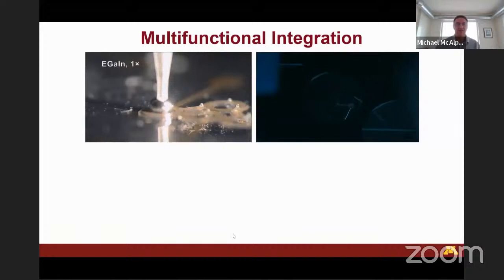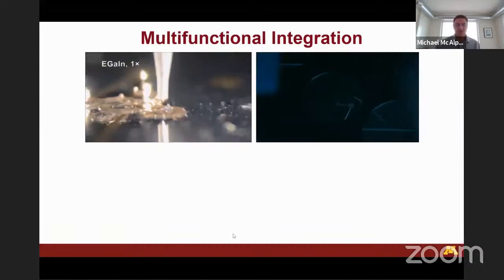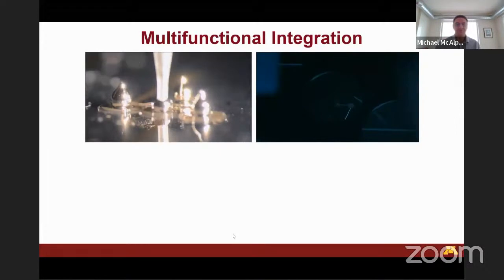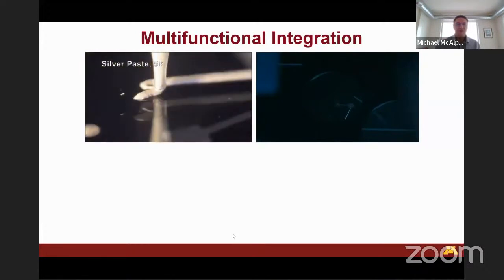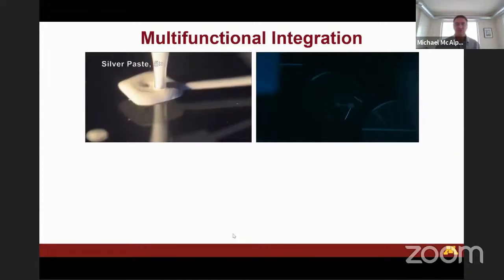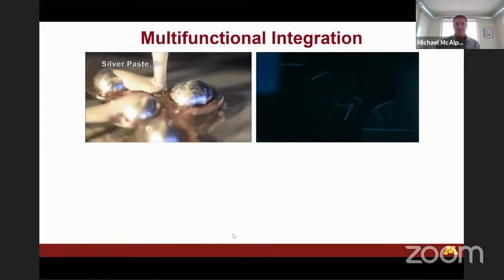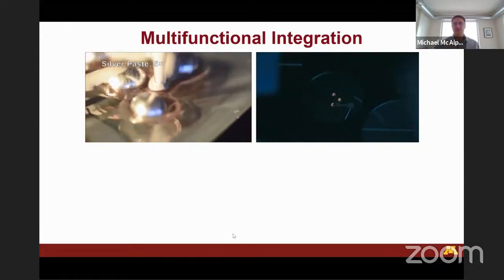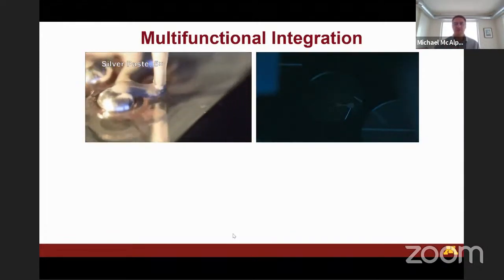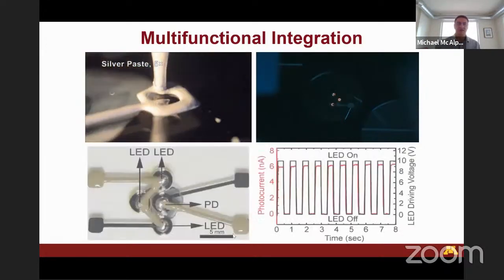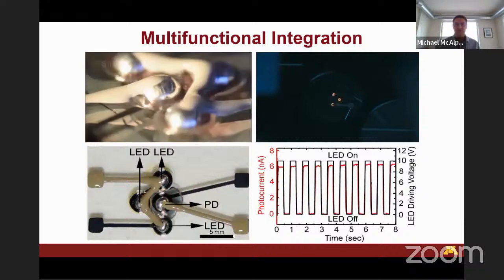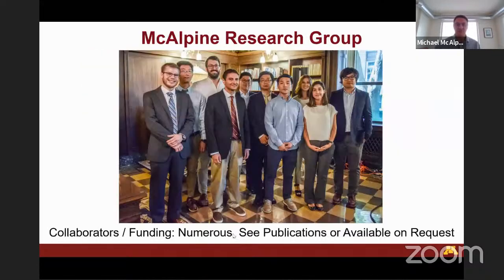The silicone, we use that to avoid shorting. This is the top liquid metal on the device. We print the silver paste on top of that liquid metal to create this integrated structure. And you can see in the right-hand movie that as those LEDs light up, those are the actual fully 3D printed LEDs lighting up. And every time they light up, the photodetector that was printed actually responds to that light. So I'm excited about where this is going. I think there are many applications. We still need to understand better many different things, the materials integration, and what really are the important applications?